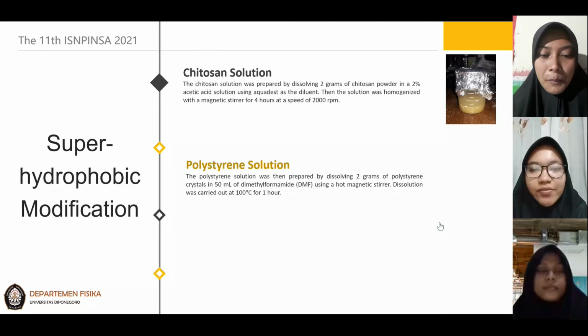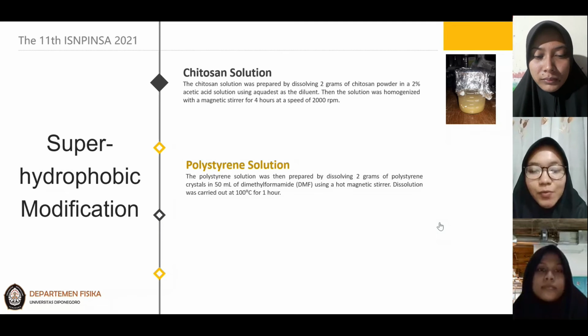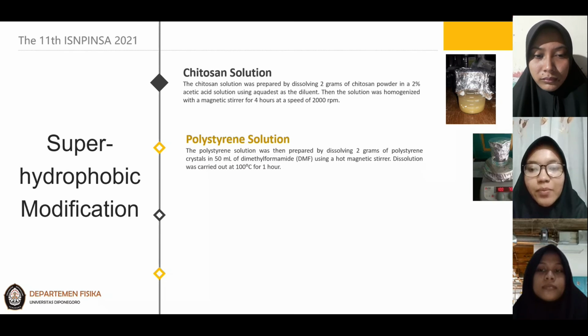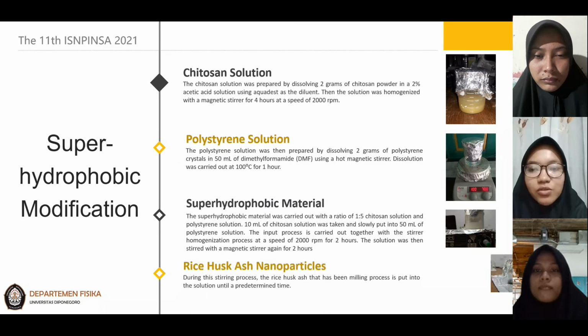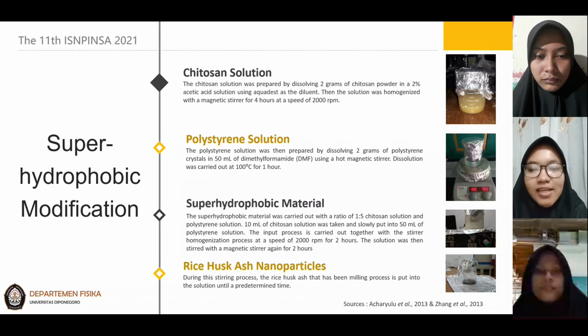Superhydrophobic modification. The first step is preparing chitosan solution by dissolving 2 grams of chitosan powder in a 2% acetic acid solution using aquadest as the diluent. Then the solution was homogenized with a magnetic stirrer for 4 hours at a speed of 2000 RPM. Then prepare polystyrene solution by dissolving 2 grams of polystyrene crystals in 50 ml of DMF using a hot magnetic stirrer. Dissolution was carried out at 100 degrees Celsius for 1 hour.